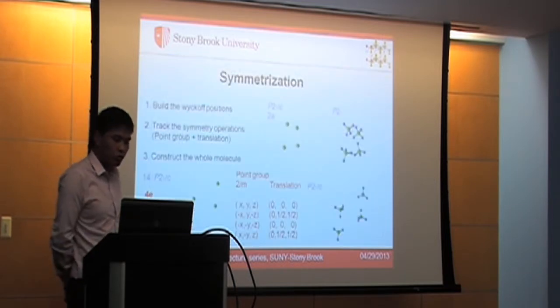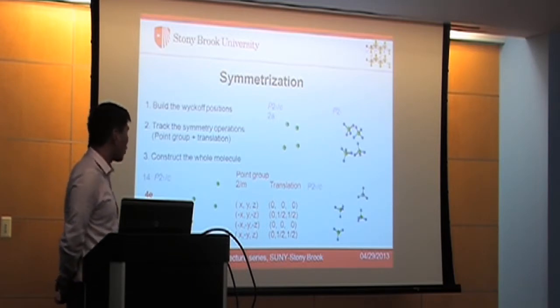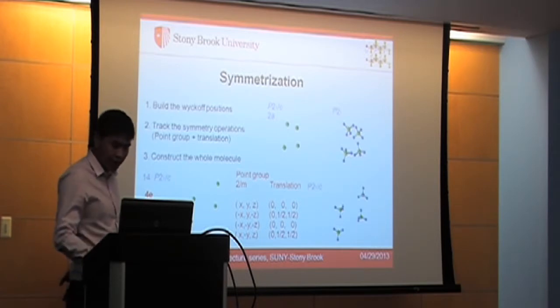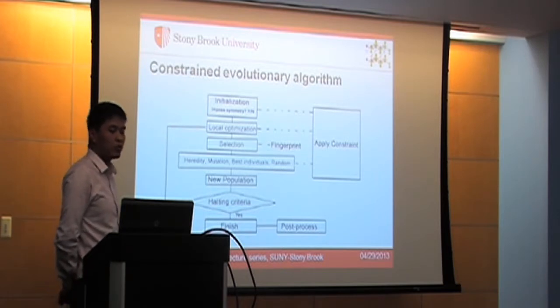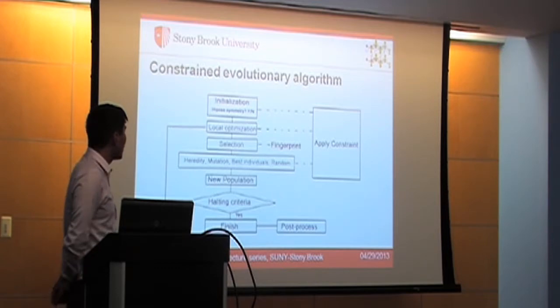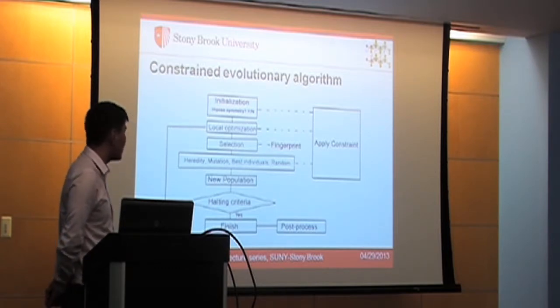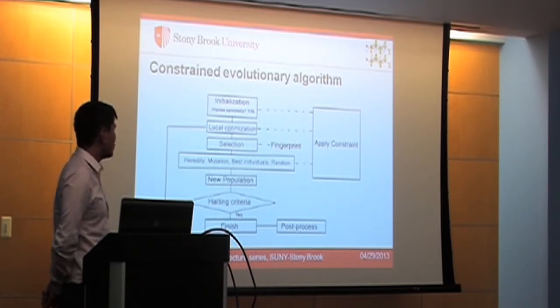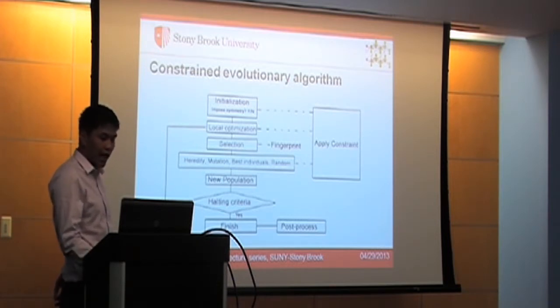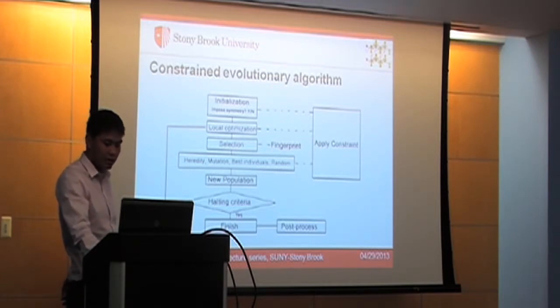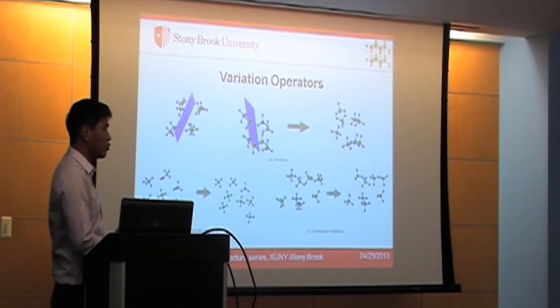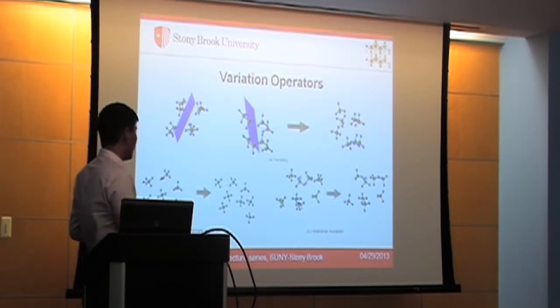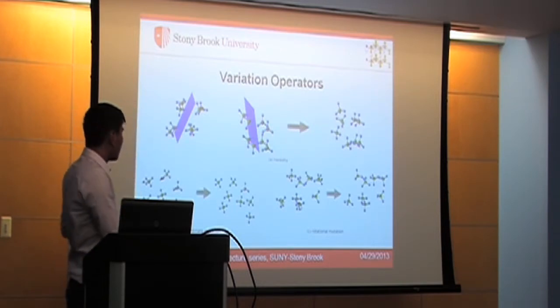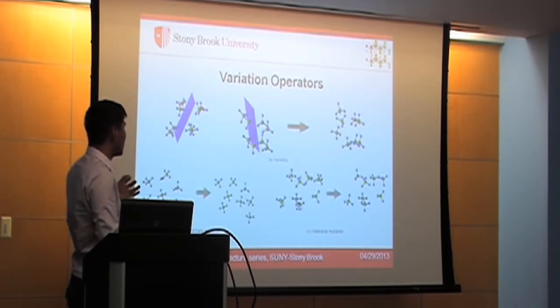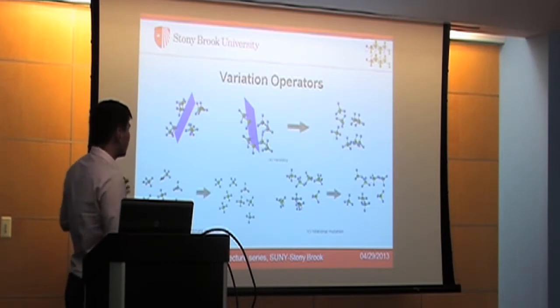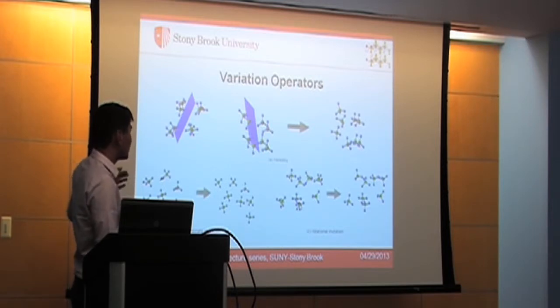So we invented an approach to construct symmetrical structures according to the desired space group. And then we can further construct a new algorithm, a constrained evolutionary algorithm, to predict molecular crystal structures. This algorithm is quite similar to the standard evolutionary algorithm. The only difference is that we apply constraints at several key stages, like initialization, local optimization, and the variation operators. Remember that when we generate new structures from parents, we have a set of variation operators like heredity and mutation. In this case, we use the same approach, but with a different technical implementation. We treat the molecules as building blocks, and the building block always keeps the same geometry during these variation operations.